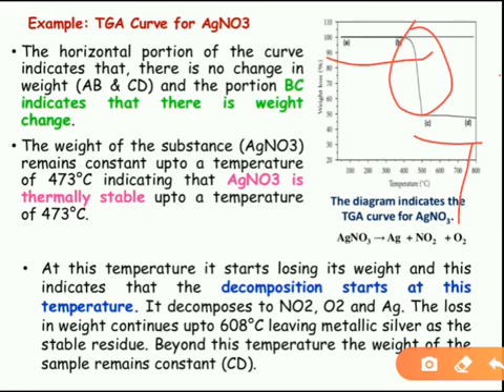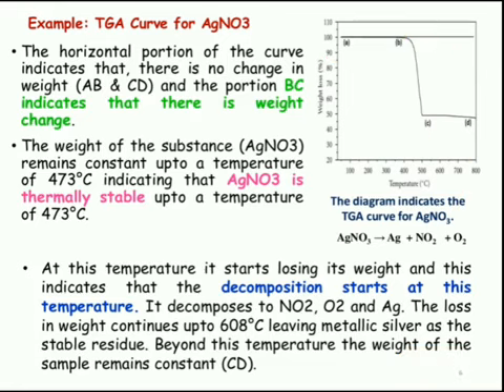At this temperature, from 473 degrees Celsius onwards, the sample starts to lose its weight, and this indicates that the decomposition starts at this temperature. Then the silver nitrate is decomposed into silver, NO2, and oxygen. The loss in weight continues up to 608 degrees Celsius, leaving metallic silver as the stable residue. Beyond this temperature, the weight of the sample remains constant.